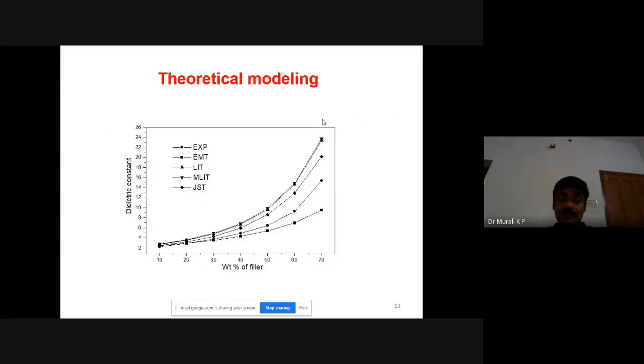Another thing is that we can model the dielectric constant according to the final dielectric property you want, and accordingly, how much volume percentage of filler has to be incorporated in the polymer matrix. There are several models based on polarization mechanisms, particle size, and so on. If you want the effective dielectric constant of the polymer and the volume percentage of filler incorporated in it, we can roughly calculate it using this theoretical modeling, without doing the experimental work.